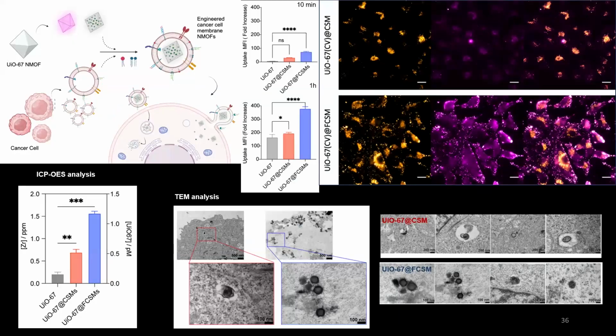It worked very well. I have data with the amount of zirconium inside the cells, but basically this is the easiest thing. You have the MOF with something that is pink, crystal violet, and the coating with the cell membranes. And this is what you get when you don't make it fusogenic. And when you make it fusogenic, you see that the content is spread in the whole cell. Okay? So it's basically because it didn't follow an endolysosomal route.